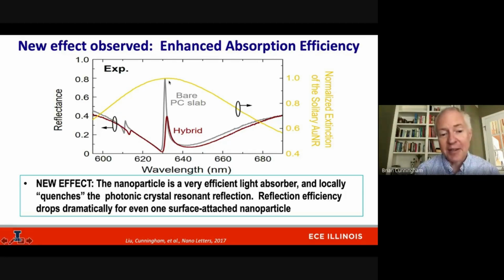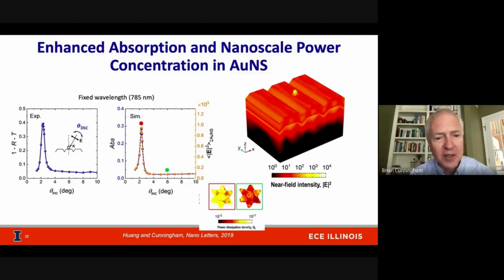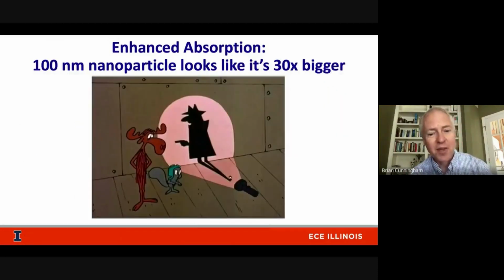And so we can observe this in the aggregate by just looking at the reflection efficiency from the photonic crystal dropping down like this. In fact, we studied this recently in a lot of detail to try to quantify the absorption cross-section of gold nanoparticles on photonic crystal surfaces. We showed in a Nano Letters paper, if we measured carefully the absorption, which is 1 minus the reflection minus the transmission efficiency, so taking very careful measurements of reflection efficiency and transmission efficiency through photonic crystals that have gold nano-urchins on them, we were able to show that effectively the nano-urchin becomes more efficiently absorbing than it otherwise would. The basic idea here is that these gold nano-urchins are small. They're around the same size as a protein molecule or a virus, but by enhancing their absorption, by putting them onto a photonic crystal, something small looks like it's actually 30 to 50 times bigger than it really is.